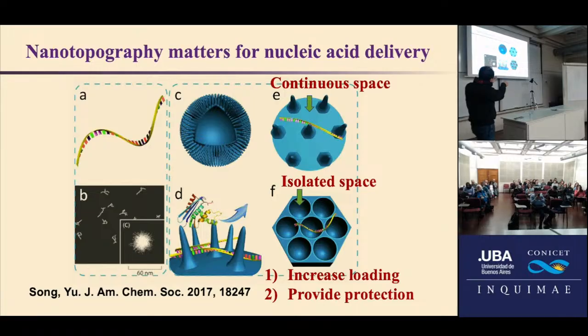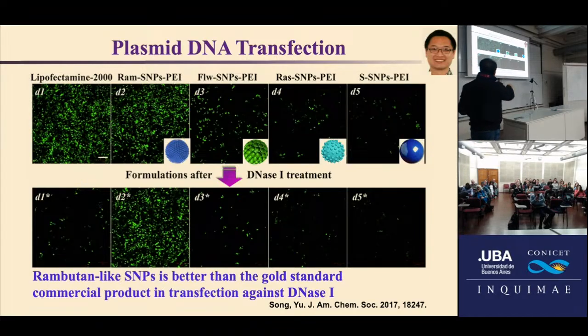And also, if we can control the spacing between the spikes, when this distance is small enough it can provide a steric hindrance effect against some enzymes, so the stability can be improved. We use this design principle for DNA transfection. The model DNA expresses green EGFP, so if you can see green color, it means the DNA has been transfected to a protein with green fluorescence. You can see here our nanoparticle with this nanotopography is better compared to conventional silica nanoparticles with large pores, and of course compared to the non-porous one, and comparable to the commercial gold standard.